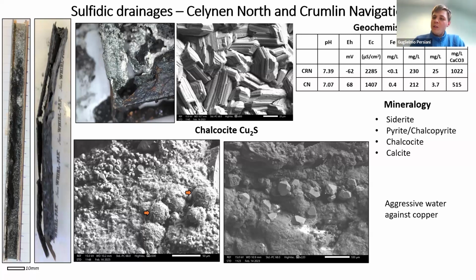On this site, of course, we don't see any iron oxide precipitated on the surface, because under those chemical conditions the iron does not exist as dissolved. It has already precipitated much earlier as sulfide. So the chemistry here is dominated by the sulfide-sulfate couple, and the corrosion is very high. We can see here the picture of the channel after 10 months of incubation. Of course, we did many replicates. We inserted many replicates of copper channel into the drainage, and that was the only one we were able to retrieve. Most of them just completely dissolved.